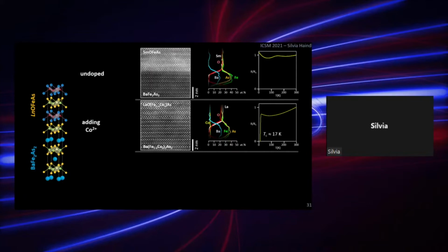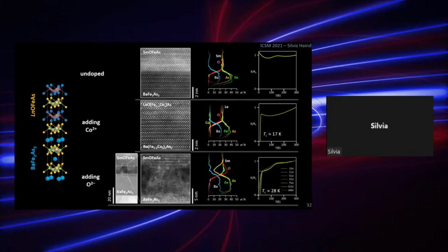The situation is completely different when we have an imbalance of anions. And here you see a very good example of cation-anion asymmetry. So if we add additional oxygen anions in the deposition of the upper layer, we find that the upper layer is partially consumed by the interface layer formation. And you can see the interface layer formation. It is about 10 nanometers thick, so it's quite large here.